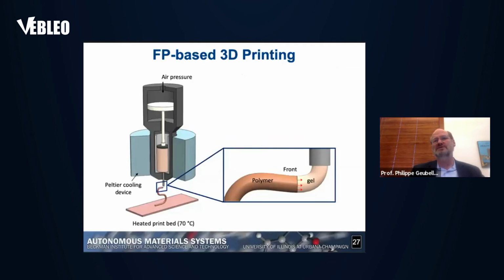Let me finish by just showing 2 or 3 slides on another type of application of this particular approach, the frontal polymerization approach, which is based on 3D printing. The idea here is that we could use this approach to manufacture free-form objects of complex shapes. The idea is you can do 3D printing by having a colder gel that is kept at a fairly low temperature over here that is printed. And as the material is being printed, we have the front that just follows the printer process.